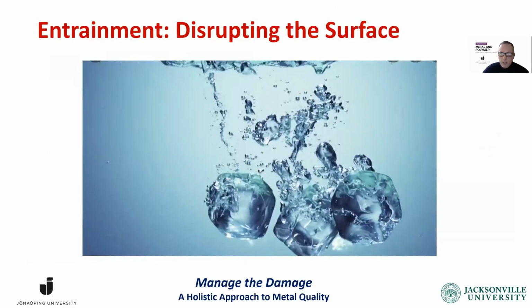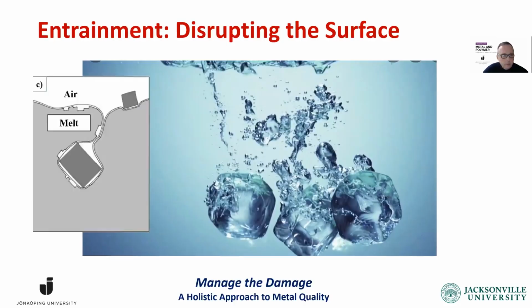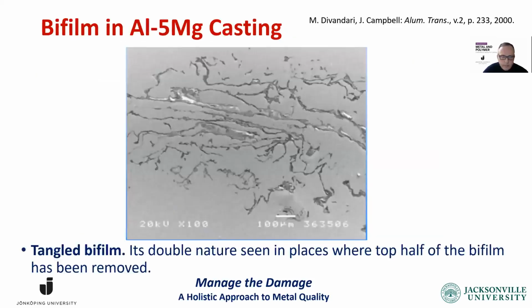So when we disrupt the surface of water, let's say we throw in ice cubes, it would be similar to putting reject material or the gating system into the liquid melt. You'll see that it leaves trails of air, and in the case of liquid aluminum, it would be air plus the trail of oxides that goes in. So the disruption of the surface is not a good thing. In the end, we have these bifilms entrained into the structure.